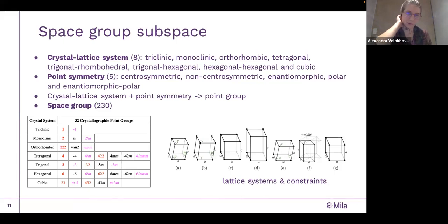Okay, now let me elaborate a bit more about the space group subspace. As I said, the main thing we want out of it is the space group, and there are 230 possible options for the space group. But the space group space itself has some structure within it, and we make use of this structure to inform the model about it. And we hope that it helps to learn the sampling of the space group better. So, let me start again. The sample in the space group consists of just three numbers, and the first number corresponds to the crystal lattice system, which is a combined parameter made from the crystal system and the lattice system.